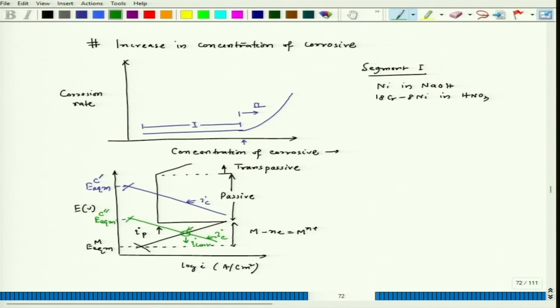Fine. So their corrosion rate would be very high, but somehow if we have some other oxidation, some other reduction process or cathodic polarization line that intersects the anodic polarization line in the passive zone, then of course this becomes my I corr, which is equal to Ip, or the passive current density, which is much lower than the I corr we observed in the situation where the cathodic and anodic polarization lines intersect in the active zone, but here it is intersecting in the passive zone. So we want this to happen in the case of active-passive material, because once we achieve passivity, it can maintain a very low corrosion rate.